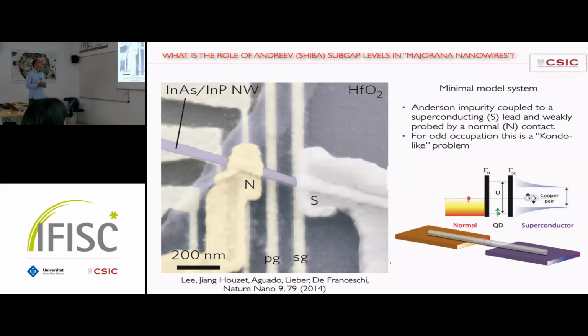All right. So the minimal model for studying a quantum dot coupled to a superconductor, which is this segment of the nanowire proximitized by the superconductor, is the Anderson impurity model, the so-called superconducting Anderson impurity model, because this is an Anderson impurity which is now coupled to a superconductor. And some of you here, Rosa is an expert on this kind of problems. The idea is that you take a minimal model for the quantum dot. You have some spinful level in the quantum dot, but now you consider this coupling to the superconductor. You have a gap, you have Cooper pairs, and you have this BCS-like density of states in the superconductor.